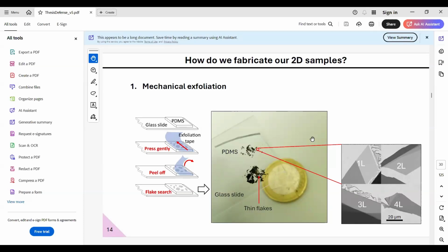And why? Good question. Because the surface facing the air has been in contact with oxygen, and therefore you are creating a very thin layer of silica. So basically you have a higher stiffness, which will help your 2D material remain flat, I would say. Of course, you could think that the bottom surface is flat, but we're using plastic Petri dishes, so I wouldn't expect them to be very flat.